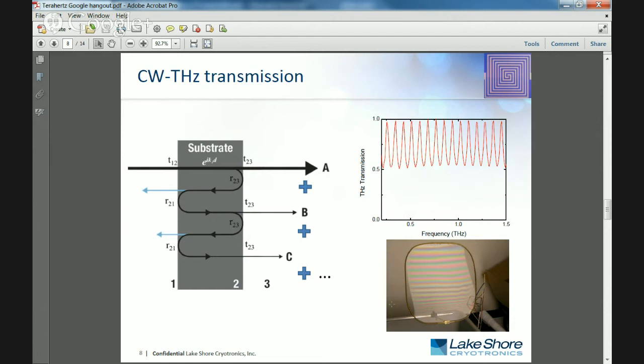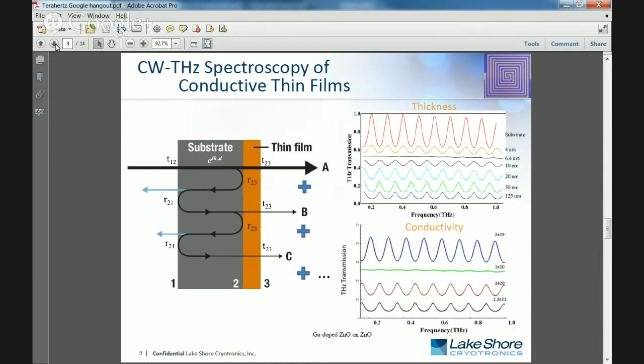Now, where we think continuous wave terahertz spectroscopy can be really powerful, if we pop over to the next slide, is the approach where we have a substrate, and now we put a conductive thin film on one surface of that substrate. What this does is modify some of the boundary conditions of these multiple reflections inside of the substrate. And depending on the conductivity and the thickness of that thin film, we see very dramatic changes in the continuous wave terahertz spectrum. Shown on the right is a film where we maintain the carrier concentration and the conductivity of that material and just make a thicker and thicker film.